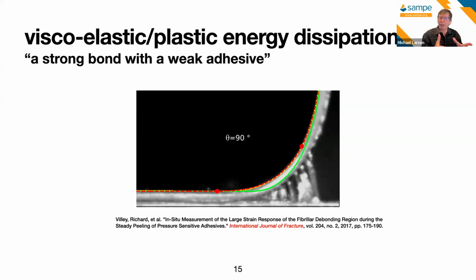And it's interesting, the material is prepared to give us this kind of resistance in a process zone area, but it's in many instances the fact that we have a bulk material that we're adhering, we don't see this kind of gross deformation and strain surrounding the substrate. So there's a lot to be learned by this, and certainly if you're adhering a thin film, then this very large deformation comes into play, a lot of nonlinear behavior. I would submit that in many cases, the domain, the parts we're adhering aren't going to permit that extensive deformation. Yet remember, the material is still providing the capability, and that's why we get a lot of dissipation going on